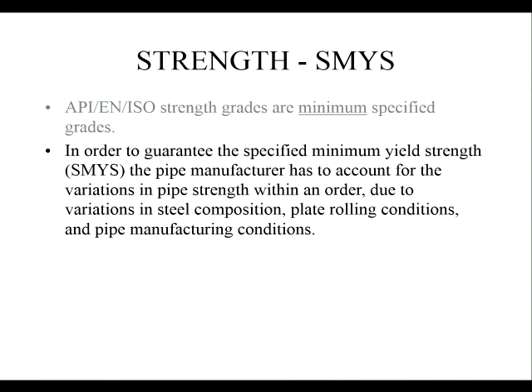So the pipe manufacturer accounts for variations in pipe strength due to variations in steel composition, plate rolling conditions, and pipe manufacturing conditions by actually trying to make a steel grade with a higher value on average of the properties and checks 3 standard deviations below the average to make sure that none of the distribution goes below the minimum value that's specified. Now it's impossible to make something that will be perfect, so there will always be the odd piece of pipe which won't meet the specification. But on average, when you sample the material, they should all be greater than that minimum yield stress.